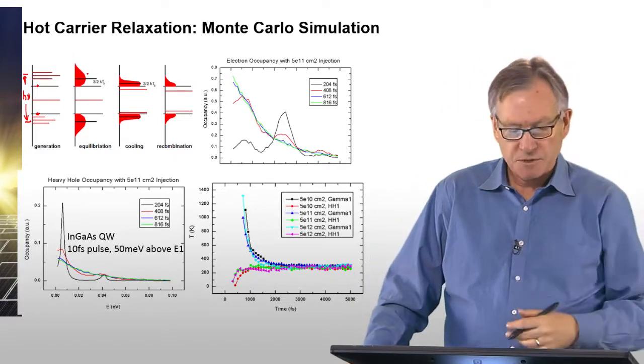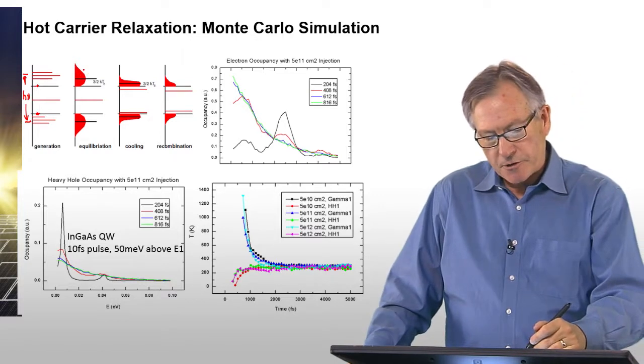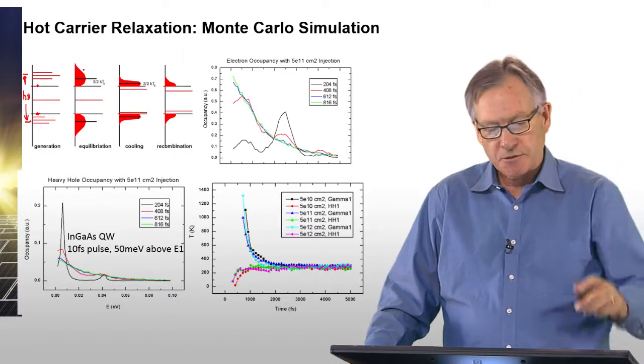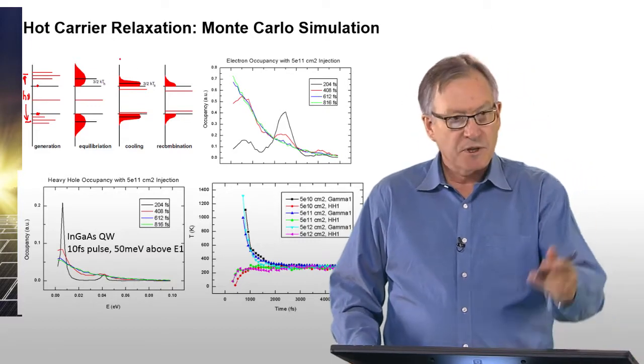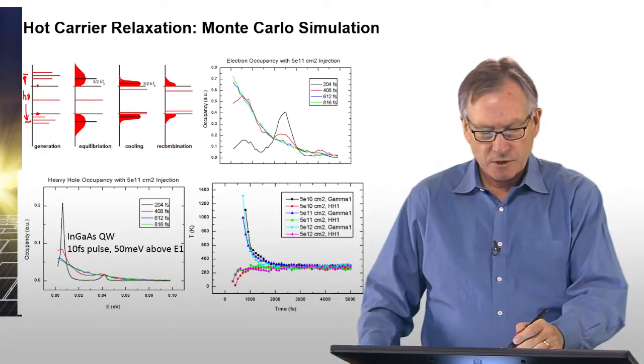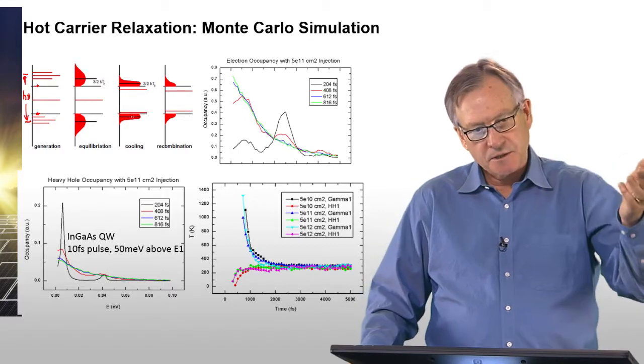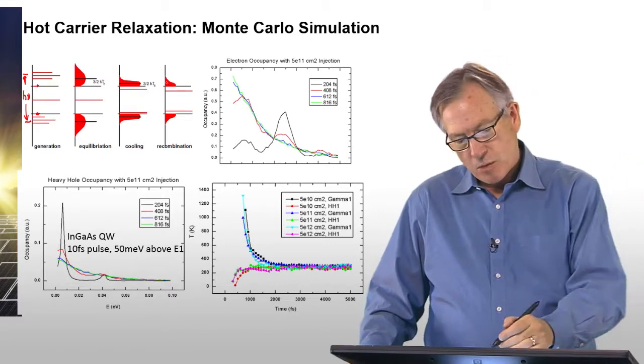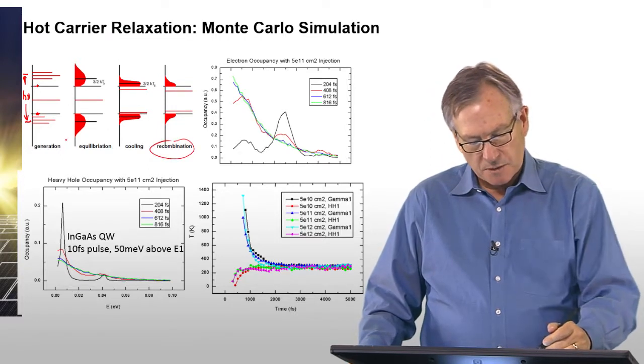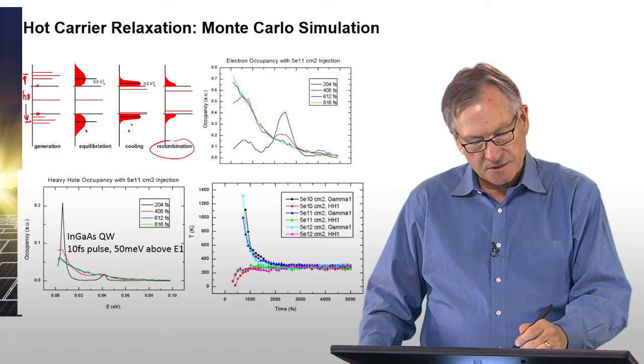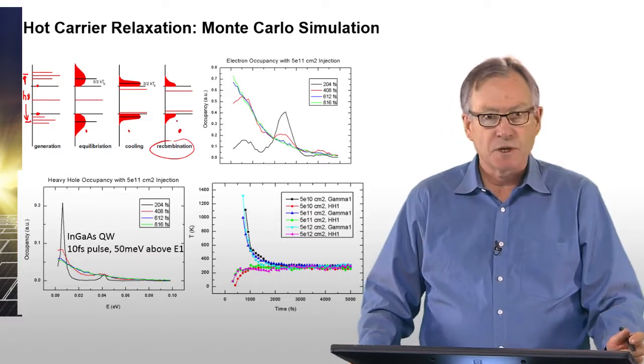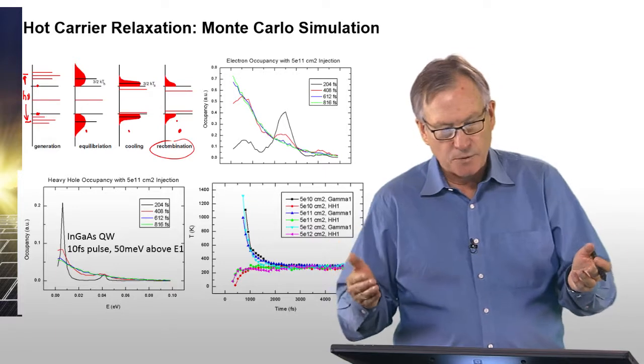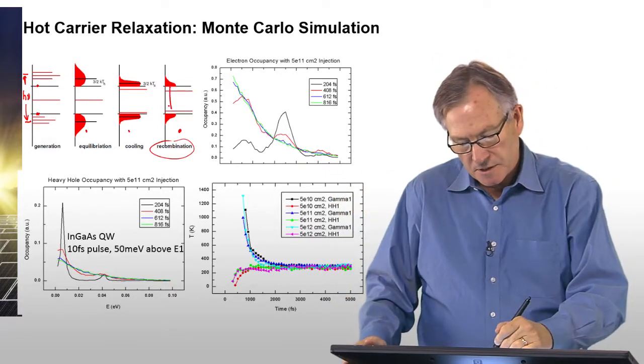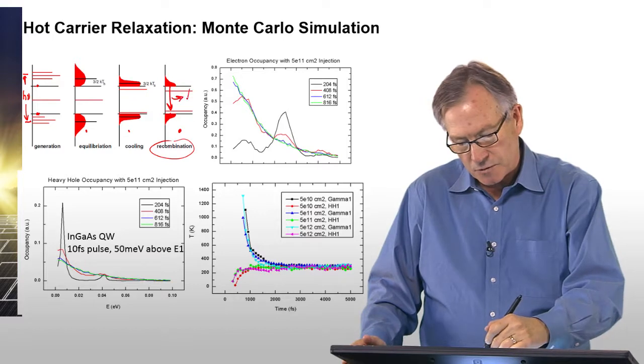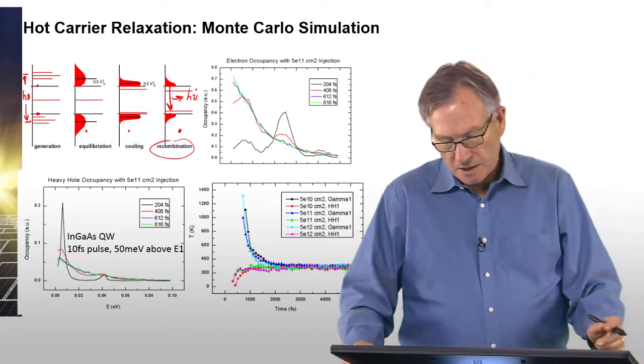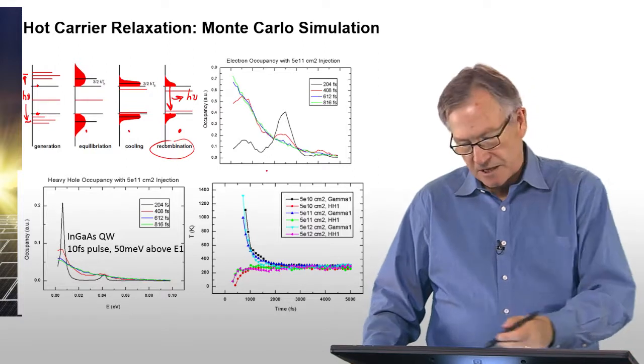So there's a time where you have an equilibrated distribution, but at a temperature that's much higher than the lattice. So it's still hot. You have this distribution of carriers, but their average temperature is much higher than the temperature of the lattice. And then over a longer time, they cool by emission of phonons, and this becomes a Maxwell-Boltzmann distribution, but at basically the temperature of the lattice. And at very long times, so this is basically picosecond, this is tens of picoseconds, and now we're talking nanoseconds when we get to this point. That's when recombination starts to take over and the population decreases because electrons recombine with holes and give off photons or thermal energy.